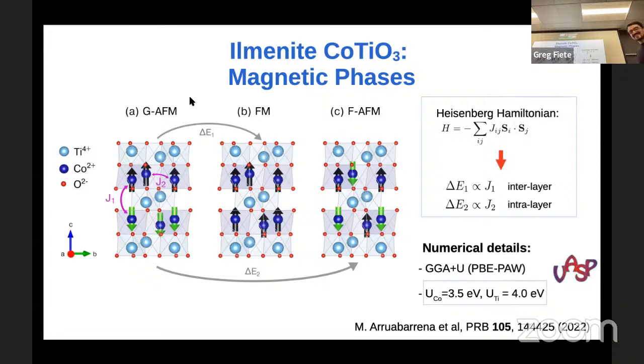Well, I forgot to tell, but we do all of this by using not just plain DFT, but DFT plus U, also called the Hubbard-corrected DFT, in which the Hubbard U interaction is taken into account to correct the delocalization of transition metal 3D orbitals that often happens in these kinds of systems. Here we used these values for cobalt and titanium. They are reasonable values, and even though I'm not going to show how we got there, these values were obtained after studying a wide variety of values and by analyzing the structure, the electronic structure, and band gap, so that they gave a reasonable description of the material, not only magnetically, but also electronically. So they are quite reasonable values.